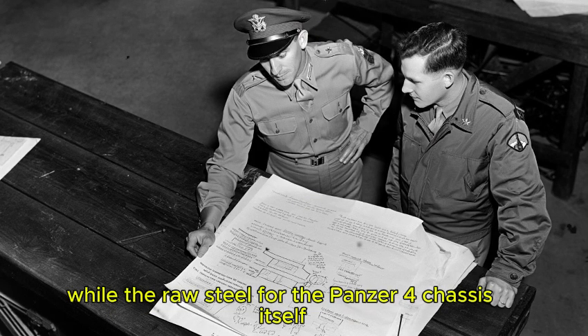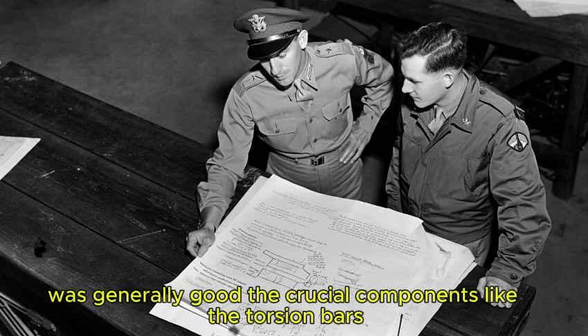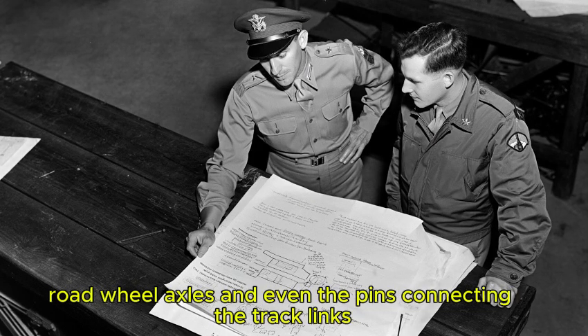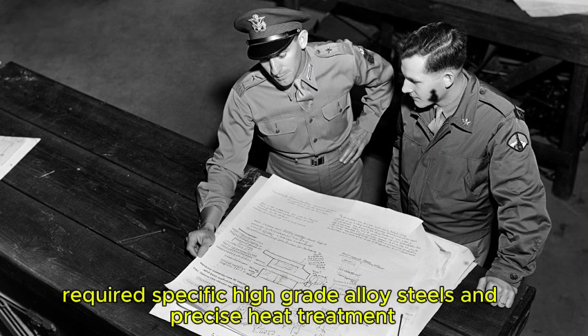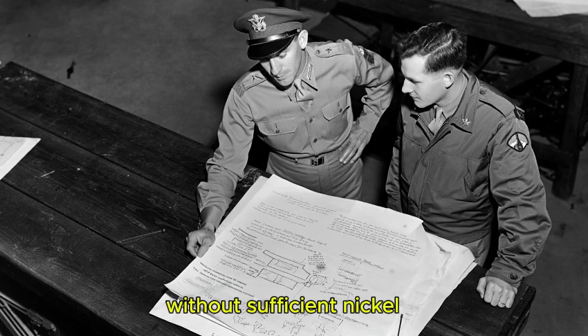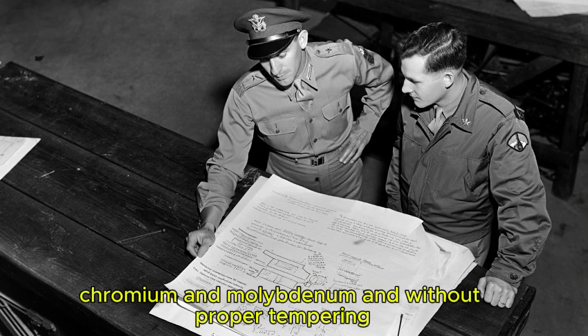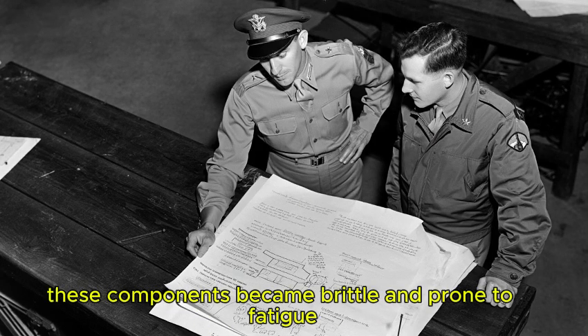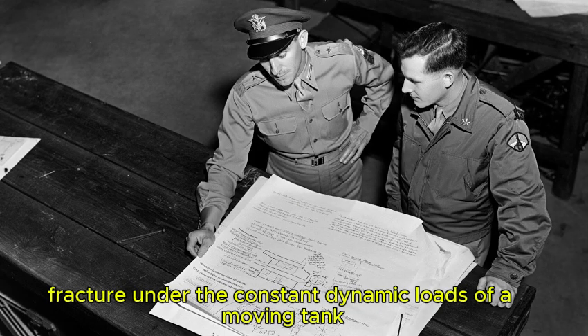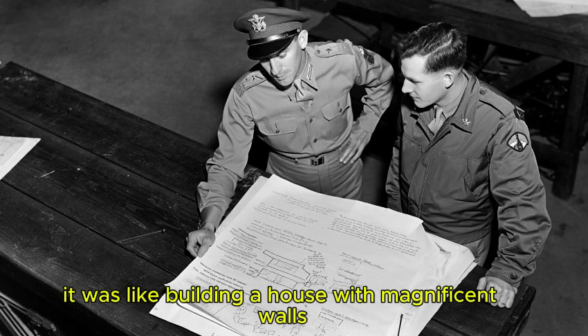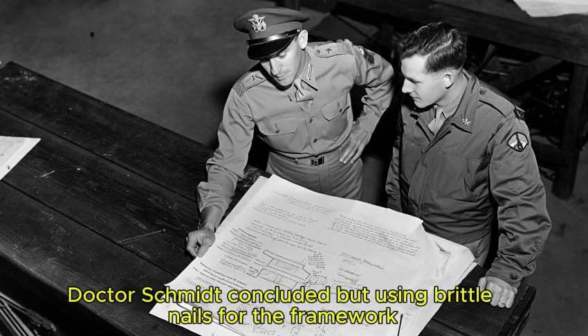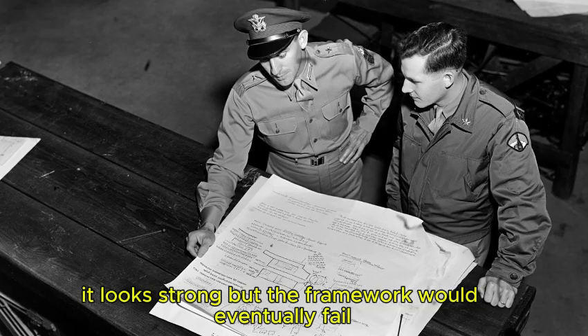Dr. Schmidt explained that while the raw steel for the Panzer IV chassis itself was generally good, the crucial components like the torsion bars, road wheel axles, and even the pins connecting the track links required specific high-grade alloy steels and precise heat treatment. Without sufficient nickel, chromium, and molybdenum, and without proper tempering, these components became brittle and prone to fatigue, fracture under the constant dynamic loads of a moving tank. "It was like building a house with magnificent walls," Dr. Schmidt concluded, "but using brittle nails for the framework. It looked strong, but the framework would eventually fail."